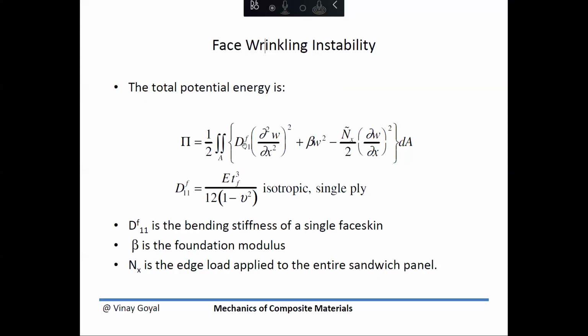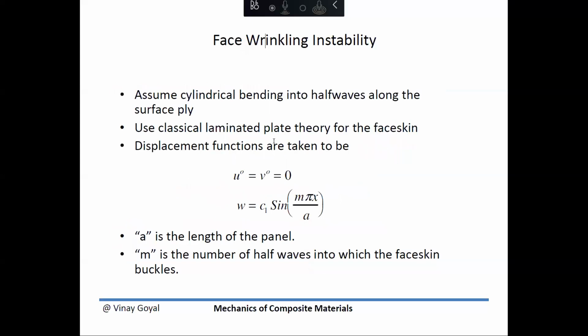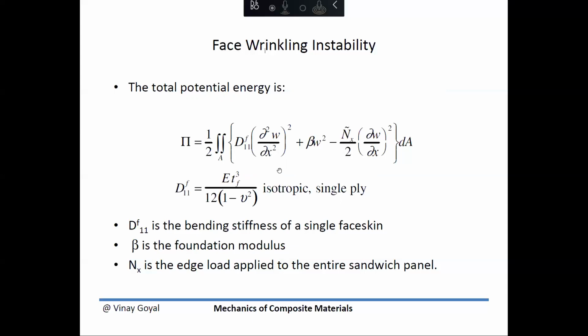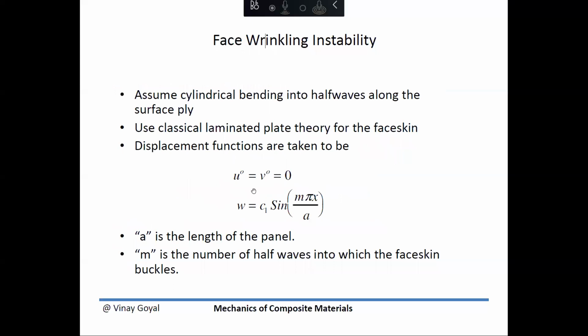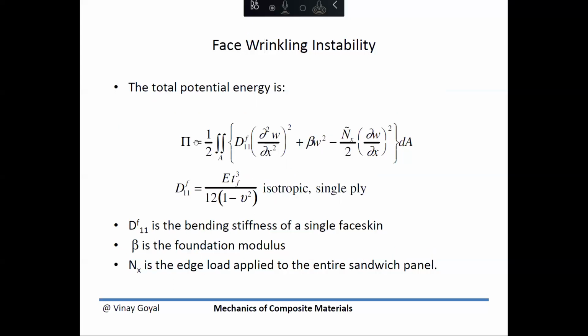Here is the total potential energy, which only depends on the deflection through the thickness. Here is the bending stiffness, and Nx is the compression load applied. So I can now minimize pi to find the deflection through the thickness. Notice how W was made up to be C1 sine. This coefficient C is not known, but this function is known. A is the length of the panel. When I plug this into this equation, I turn pi into only a function of C, which allows me then to take the derivative of pi with respect to C and set it equal to zero to find C.